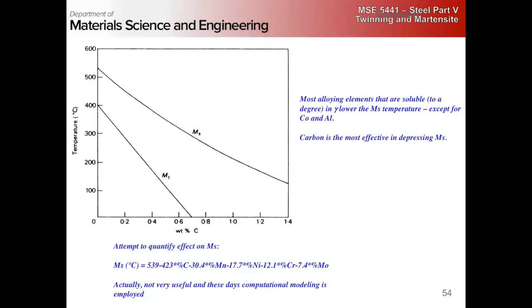There isn't room, so that's why it's tetragonal, right? Because of the huge distortion that the carbon atom makes. If you have more carbon in there, you're going to have much more distortion in your martensite structure, right? So the energy associated with that distortion stabilizes the austenite to lower temperatures. Right? Does that make sense? The more carbon you have, the more heavily distorted your structure is going to be.